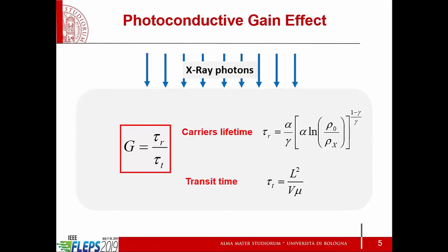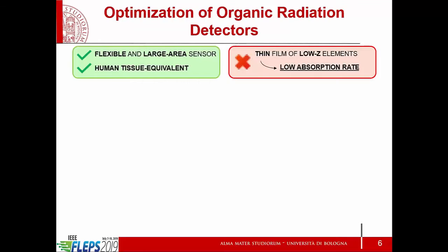This can be nicely modeled, and it works very, very well if we consider two contributions to this gain. The two contributions are given by the carrier lifetime term, this one, and a transit time term. The ratio between these two provides the gain. As you see, the bottom term is mostly related to the mobility and the geometry of the device, while the top term relates to the charge density and alpha and gamma, two parameters related to the trapping effects of the traps.